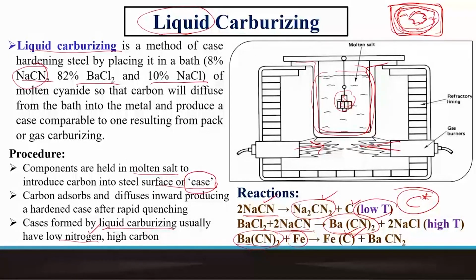So the point of distinction here is the liquid state, the charge that we are dealing with, and the temperature at which we do it. One very important point, and that's absolutely not to be missed out at all, is that we have a lid which has to be completely hermetically sealed so that there's no escape. This is absolutely not to be allowed, because of sodium cyanide, and even inhalation of that vapor can lead to not only disaster, instant death.